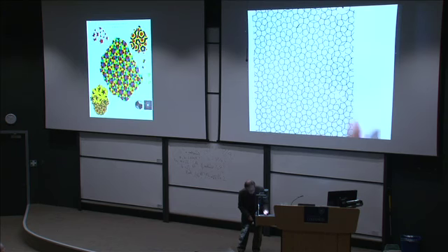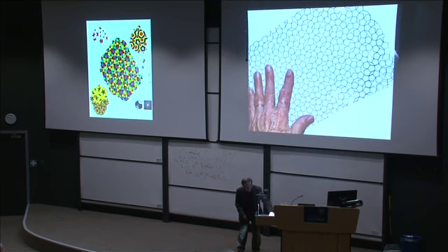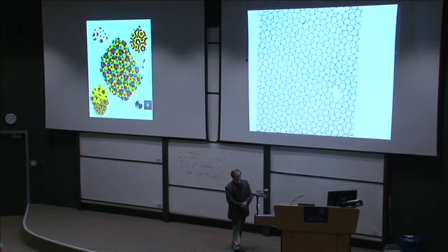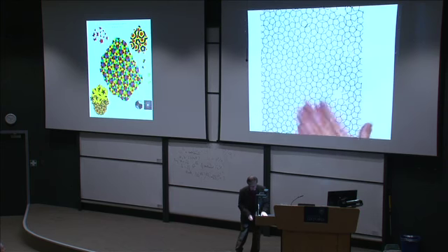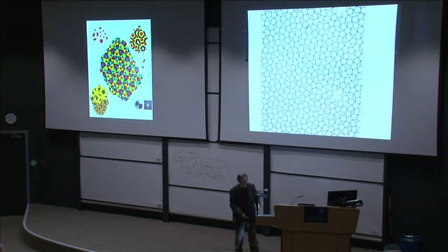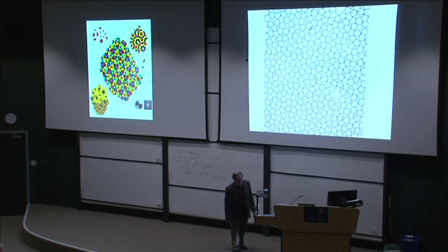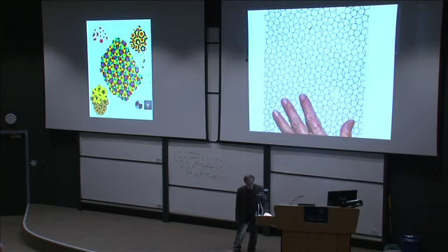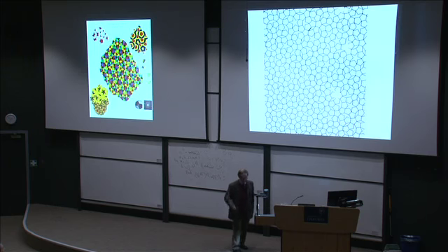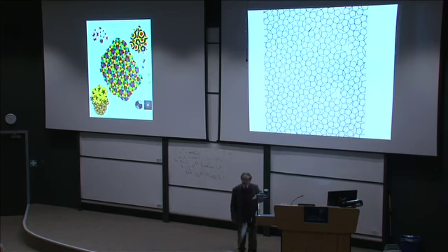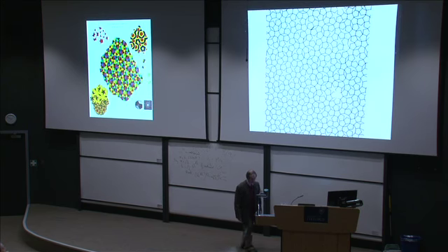And I find another translation, and it will agree to 99.9%. And also, I should say rotation. I can find points about which it will rotate, and the symmetry in the first case would have been 99%, secondly 99.9%. And you might say, well, no, I meant 99.99, 9999, whatever you like. There will be a translation and a rotation of this pattern, fivefold rotational symmetry and a translational symmetry to that precision. So it's almost in that sense never quite exactly 100%, but anything slightly short of 100%, yes, you can find it.